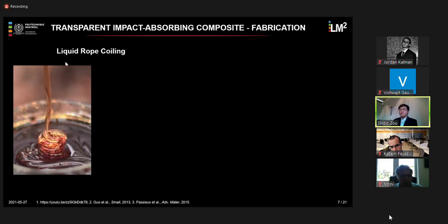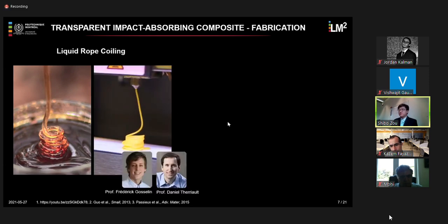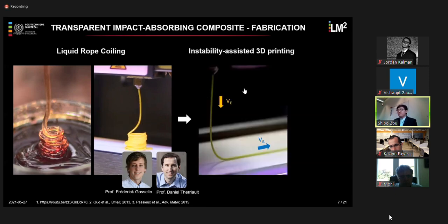This is when you deposit a viscous thread from a certain height onto a horizontal plane. Due to the compressive stress along the thread, buckling instability will be triggered, and the material will start coiling before touching the ground. And my previous PhD supervisors, Professor Frederik Gosselin and Professor Daniel Therriault, found very similar coiling phenomenon on the FDM 3D printer. And then they further deposit this molten thermoplastic polymer onto a horizontal plane, a moving horizontal plane.